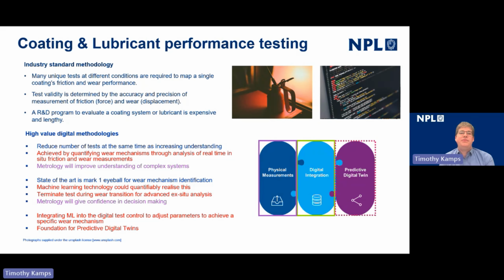And then a repeat test will be run, and the test will be stopped at a condition that meets that criteria, and the surface is evaluated to try and understand that transition. This after-the-fact analysis is quite time consuming, but it also involves quite a lot of trial and error, as stopping an experiment that's in motion at a very precise point using analysis after the fact can be quite challenging.